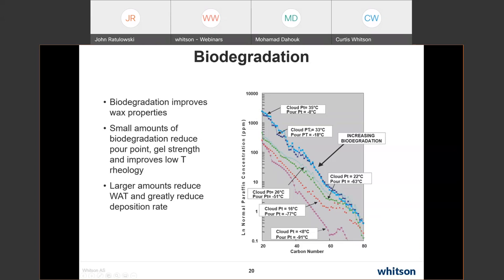If I have partial biodegradation where I remove a lot of the lower molecular weight normal paraffins, it actually impacts the pour point or the gel strength first. So you see in this area where I have intermediate biodegradation, my pour point is really low. But my cloud point, yes, it's come down some, but it's not come down as much as the pour point. So I have 22, 26 degrees here as compared to 30 and 35 degrees. Now, when I get to severely biodegraded systems, both the cloud point and the pour point drop substantially.